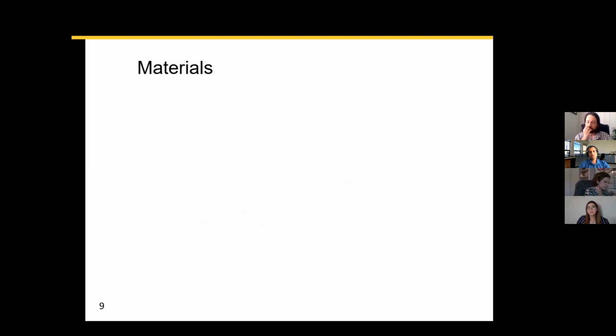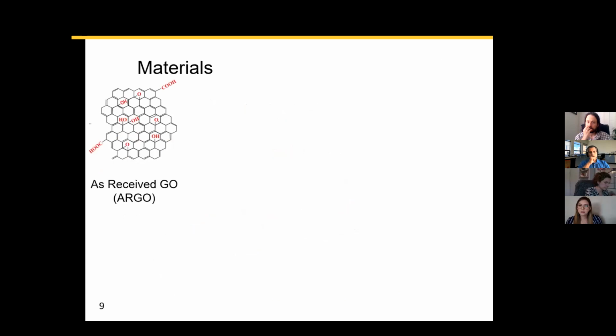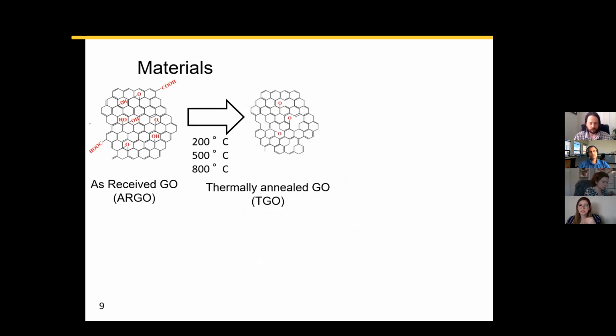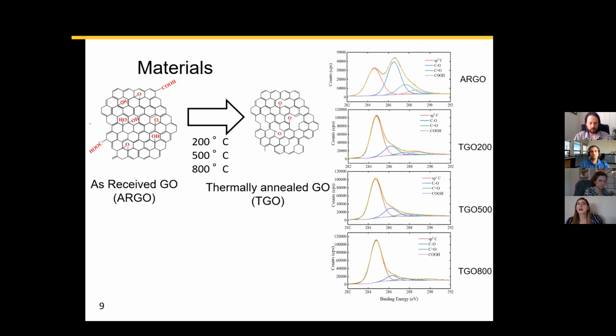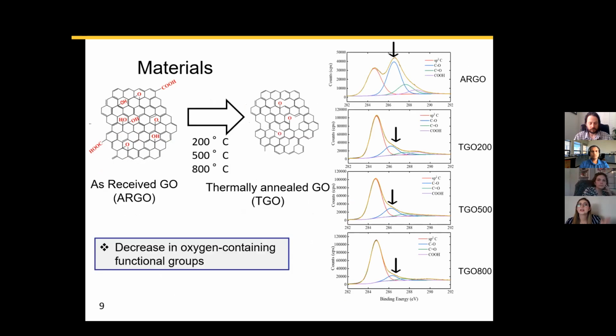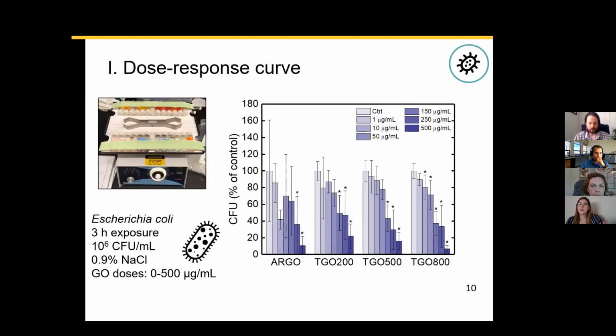So for this work, we are going to be working with a commercially available graphene oxide material, which we're going to call as-received GO. It's a highly oxidized material that we will then thermally anneal at different temperatures, namely 200 all the way to 800 degrees Celsius. This thermal annealing basically reduces the material in a systematic way. Upon surface characterization, we see that the oxygen content decreases as we increase the annealing temperature. So now we have 4 different materials that are systematically reduced, and we're going to continue to analyze how they interact with bacteria.